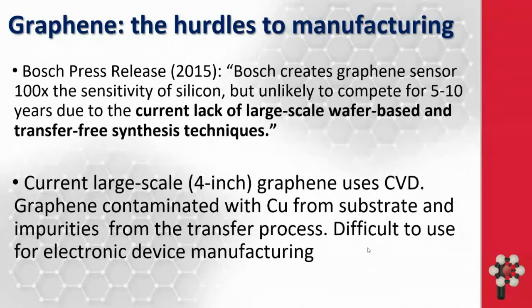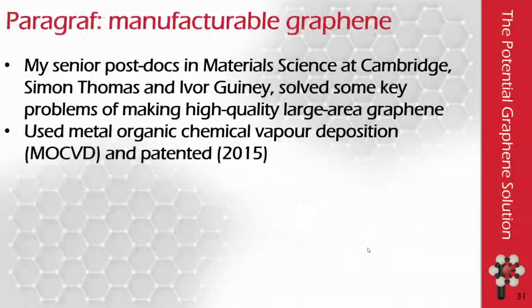I gave this as a sort of challenge to my group and said, we need a new way of making graphene. And we were using equipment called MOCVD to make gallium nitride, metal organic chemical vapor deposition. And one of them came to me one day and said, why don't we try this? And I said, well, it's probably not going to work, but why don't you try it? And it did work. So this was a postdoc, Simon Thomas, and they used metal organic chemical vapor deposition, and we found you could grow graphene using this technique.